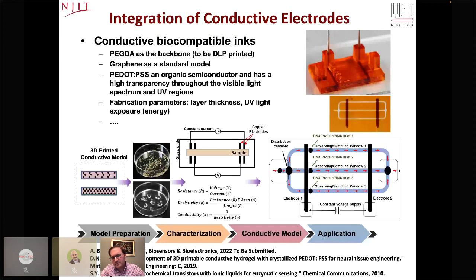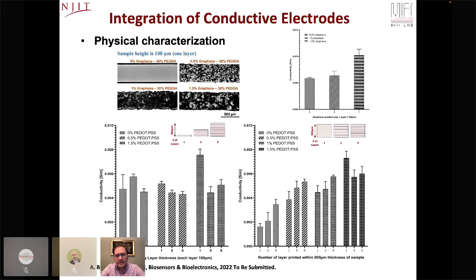And as a characterization step, we showed that the conductivity of PEDOT:PSS is comparable to, for example, graphene, a standard material model that people use as a comparison. And again, the numbers are very comparable. It shows a high quality of conductivity that we can always use.